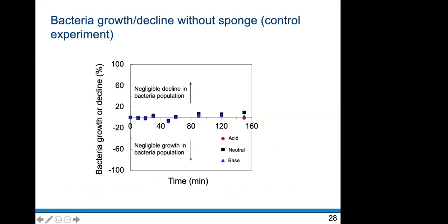This plot shows the control experiments where there is no sponge, just the LB medium, which is nutrient-rich water. This is a growth curve. Over time I monitored the cells, and this shows the cells remain constant. They are not growing; their concentration remains the same. These were measured at different pH conditions: acid, neutral, and base. This is to ensure the pH is not causing the bacteria to die, because typically they want to survive around pH 6. But if we go a little bit down to pH 4 or pH 5, would they survive or die? That's why we need to do these control experiments, and also to ensure what the actual specific role of the sponge is.